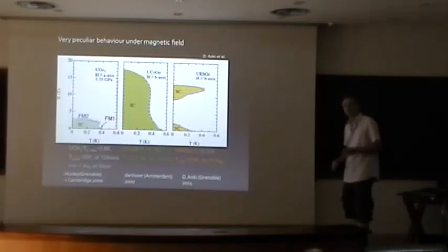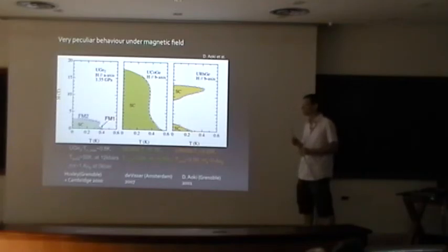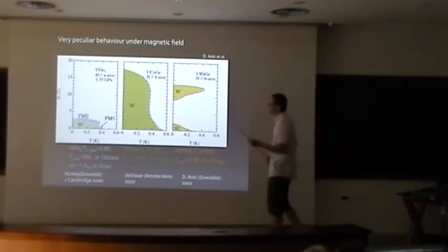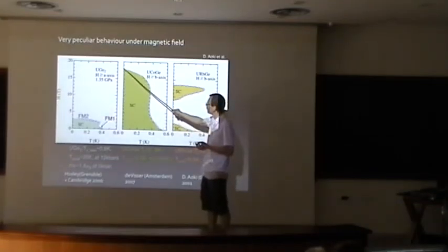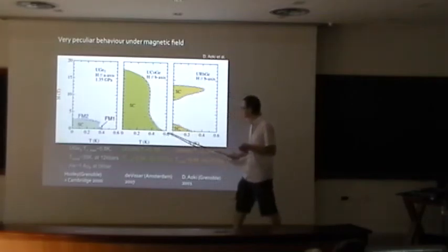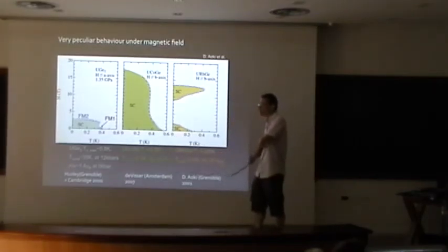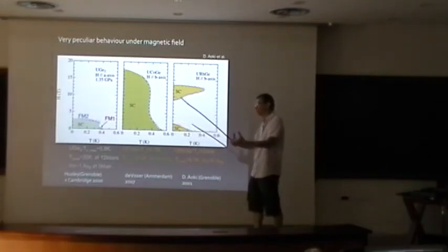Thank you. I have a question. The P-wave superconductivity that you are suggesting here, has it been confirmed experimentally? What is confirmed is more or less this superconductivity, the fact that you have HC2, which is almost 20 Tesla here, whereas TC is 0.6, so you are completely above the Pauli limit. Yeah, depending on the explanation.